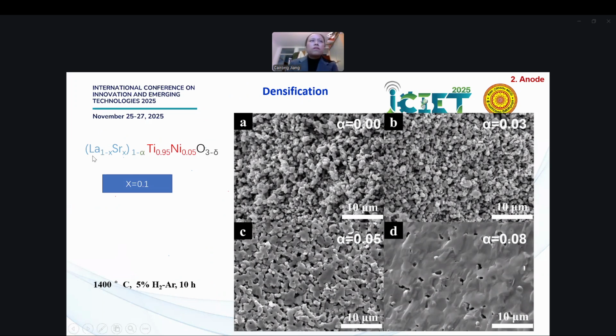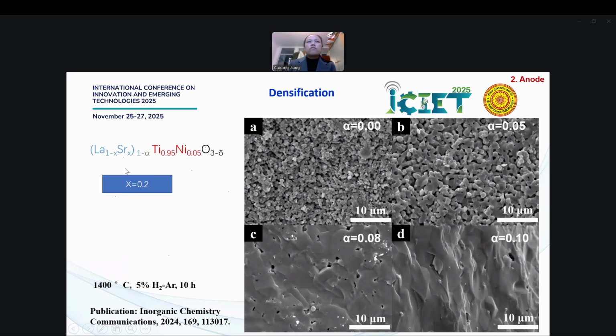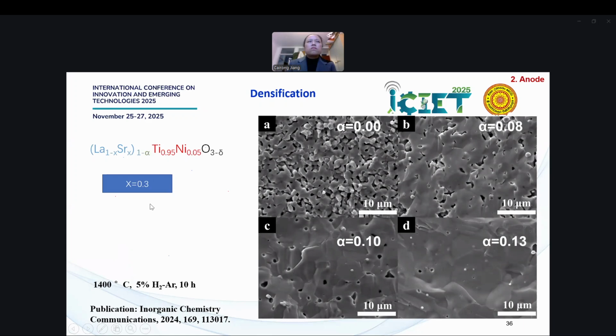When 10% of strontium is doped, sorry, I changed the expression, it's 10% of strontium, and when the deficiency alpha is equal to 0.05, you can get a dense sample, because the sintering temperature matters for the following procedure to prepare a cell. And if we increase the percentage of strontium, the alpha value increases a bit to get a denser sample. We tested these four types of different strontium content. It's easier if the strontium content is higher.